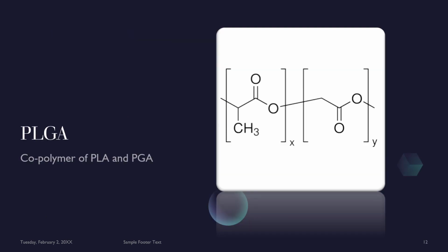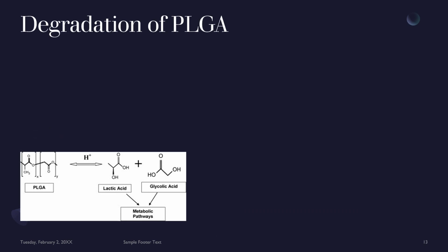Poly-D-L-lactide-co-glycolide, also known as PLGA, is the perfect example to demonstrate the variability of polymeric nanoparticles. PLGA is an ester copolymer of lactic acid and glycolic acid. PLGA is approved by both the FDA and the EMA for drug delivery due to its great biodegradability.